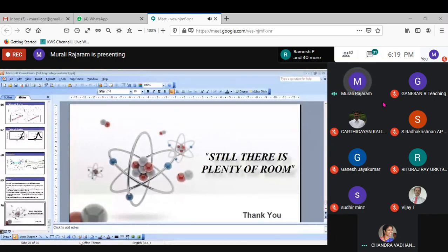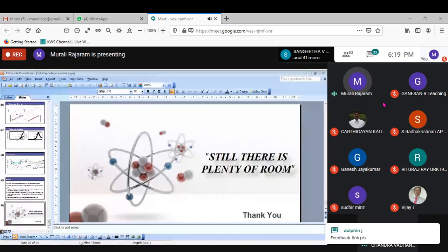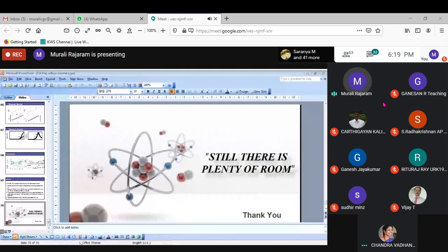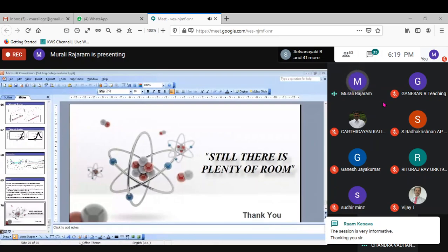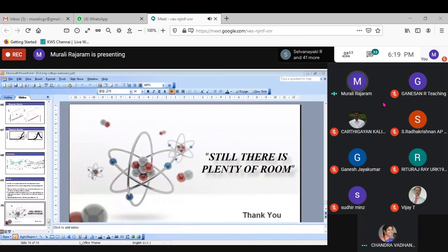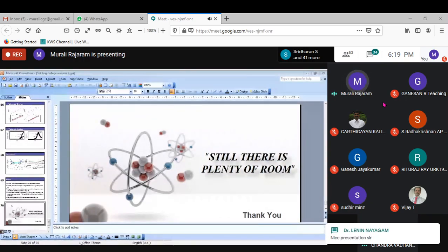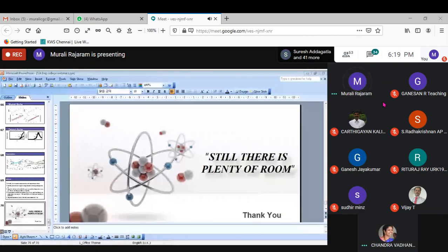Yeah, as I said in the first slide, for a magnetoelectric material you don't need a ferromagnetic and a ferroelectric material. You can have a paramagnetic material, but still you can have a change in the dielectric constant, which is called magnetoelectric, or magnetodielectric. It is not ferromagnetic. For example, take chromium oxide. This is not a ferromagnetic material, but still it is called a magnetoelectric material, because the dielectric constant changes when the magnetization changes. But for multiferroic materials, you should have both ferromagnetic and ferroelectric order.